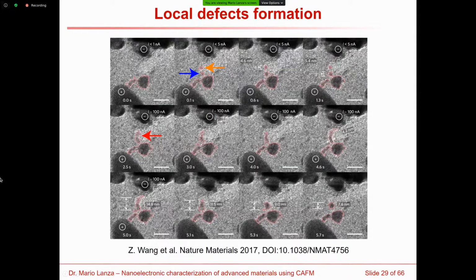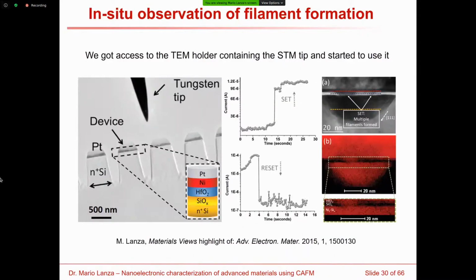This technique is beautiful because it allows you to correlate the electrical changes with the morphological changes in the dielectric, and at the same time, if you have EDX or EELS in this TEM machine, you can also detect the chemical rearrangements that have produced this electrical stress, which is wonderful because it allows you to observe in situ the switching mechanism in this material.